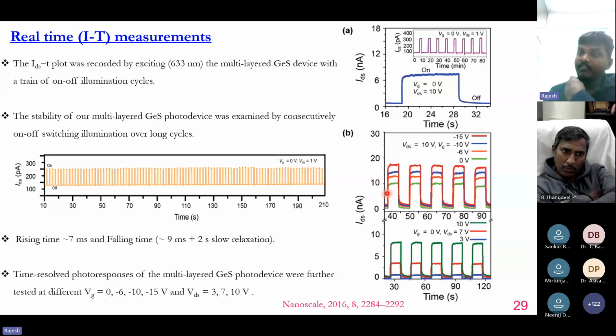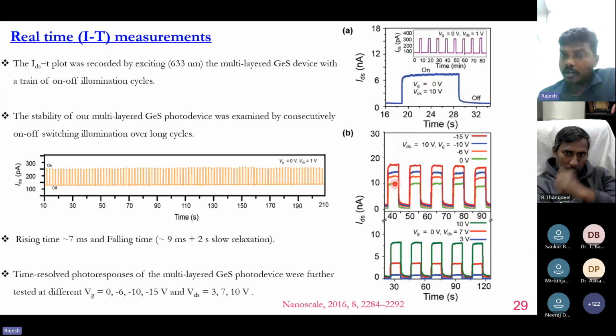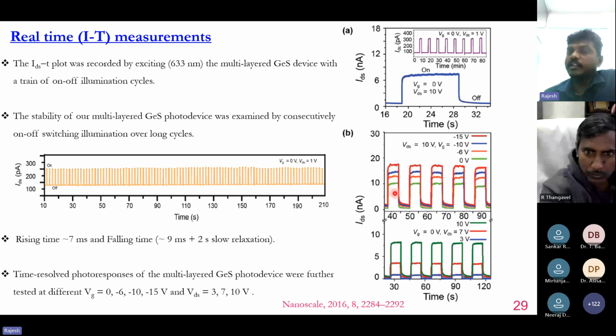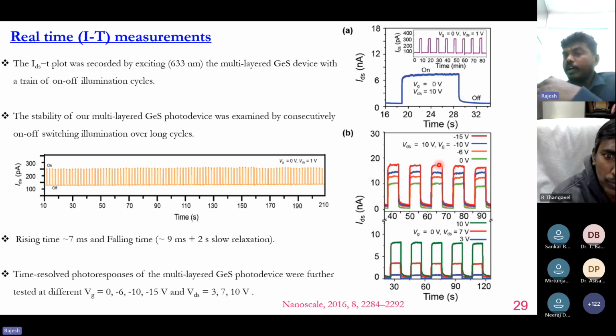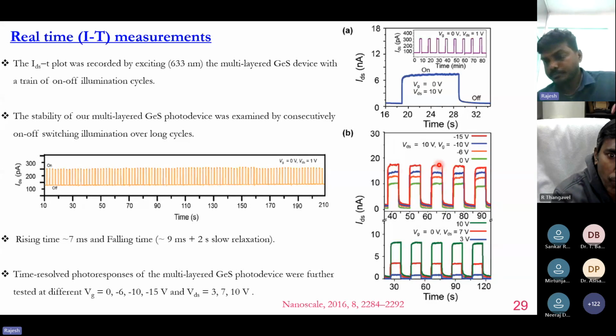And also when we vary the gate voltage negatively as well as the source drain voltage, we can clearly observe the enhancement and decrease in the photocurrent, which shows the durability of our germanium sulfide photodetector. So basically, we can conclude that this germanium sulfide can act as a stable as well as a durable photodetector for real-time applications.